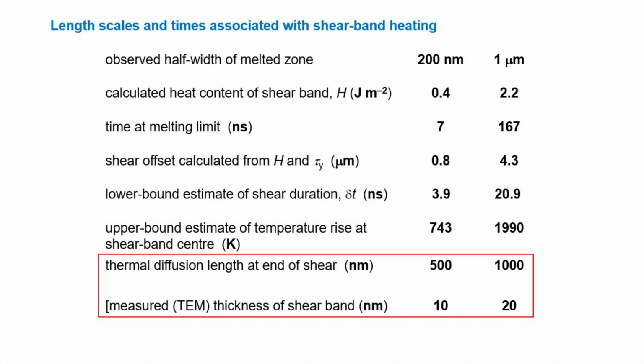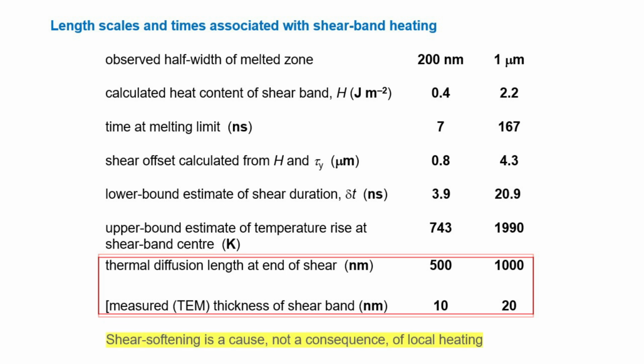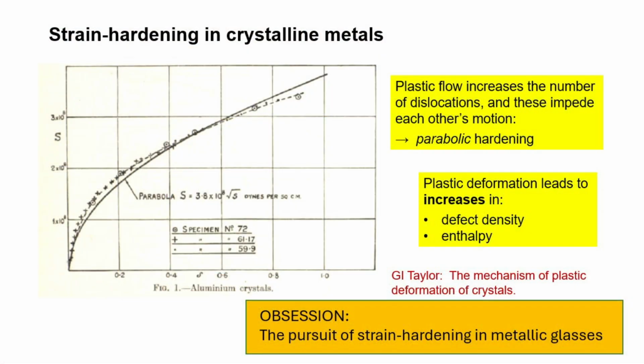We'll ignore all the detail, but just say, there seems to be no relation between the thermal diffusion length and the thickness of the shear band. So we would conclude that the shear softening is a cause of the local heating. Once you localize things, you concentrate where you get your heat, but it's not the consequence of local heating. What it's the consequence of is the shear dilation. However, it's left me with the obsession of how to get strain hardening in a metallic glass. We've so far miserably failed to do that.